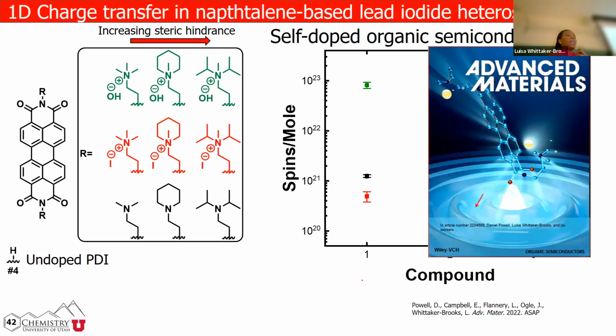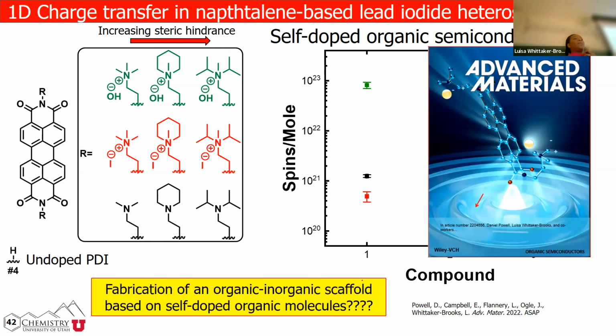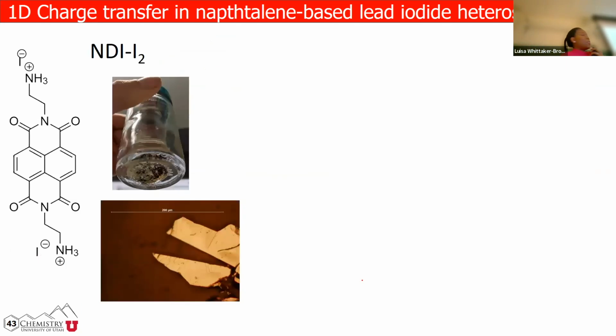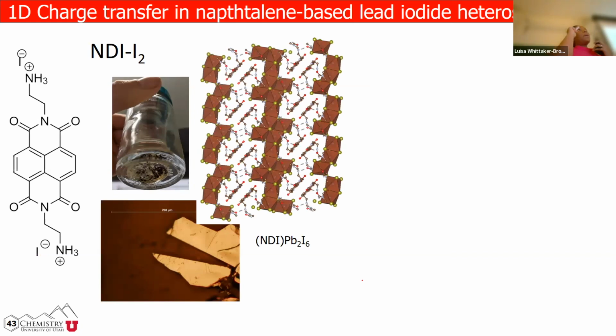Okay, so we wanted to do this, and we recently got this published in Advanced Materials, and wanted to know if we could take these molecules and combine them with perovskites to make organic-inorganic scaffolds based on these structures. All right, so we ended up making these single crystals, not with the perylene diimide, but with the naphthalene diimides, right? So it's actually smaller.